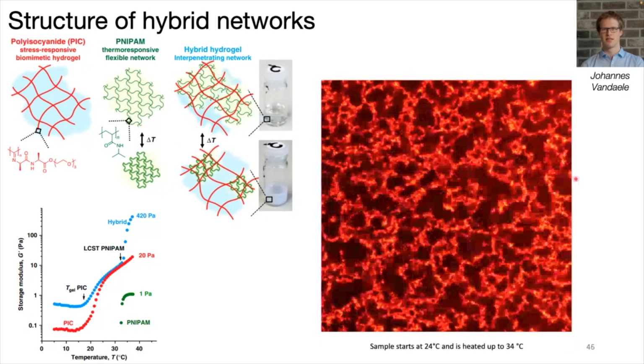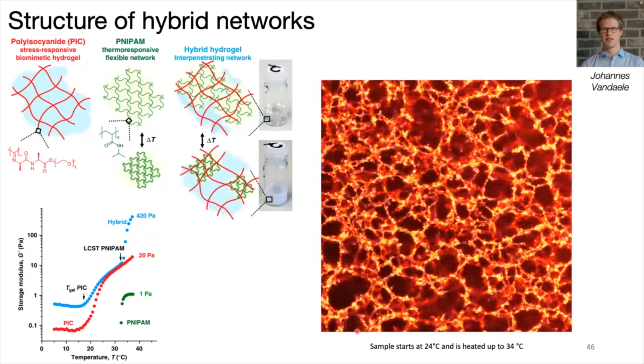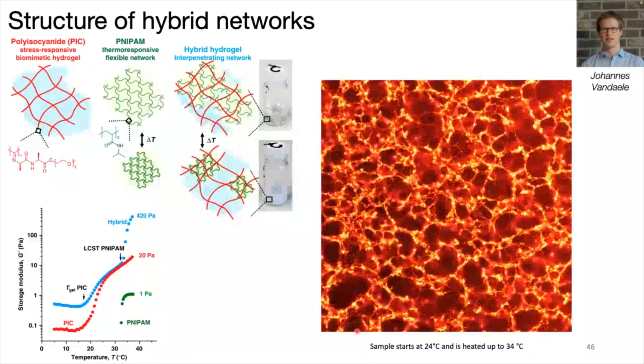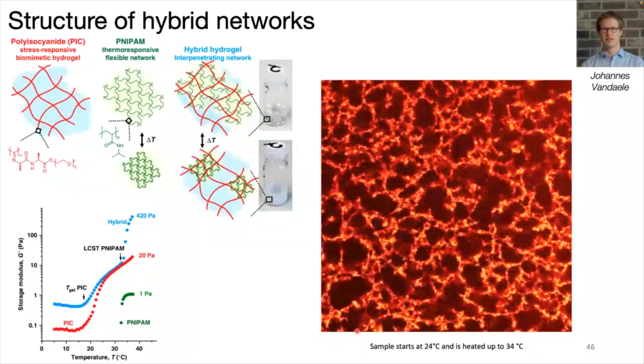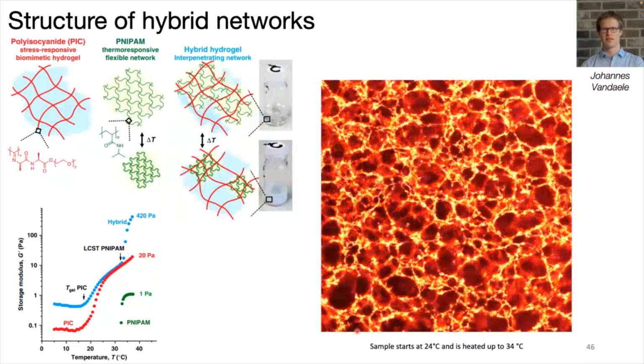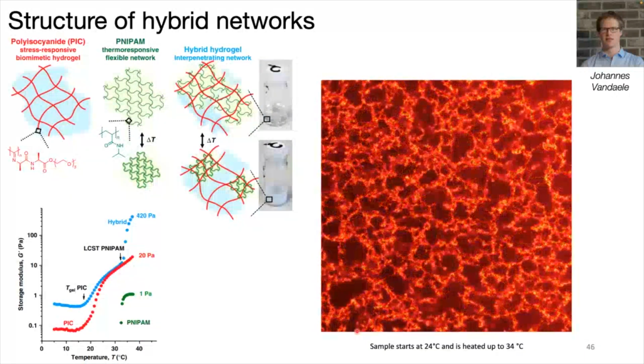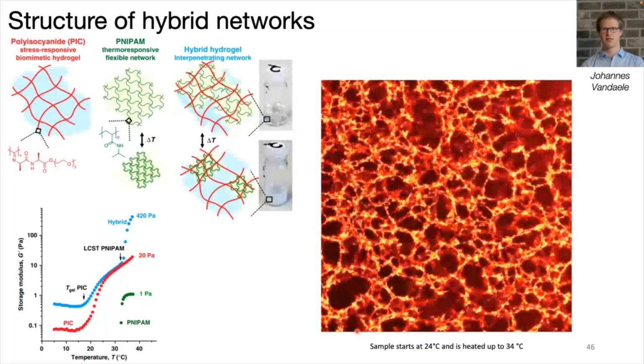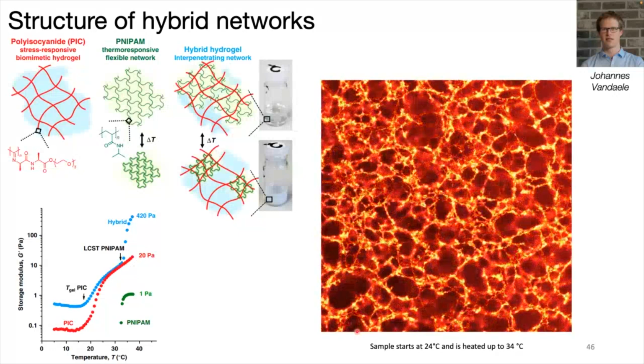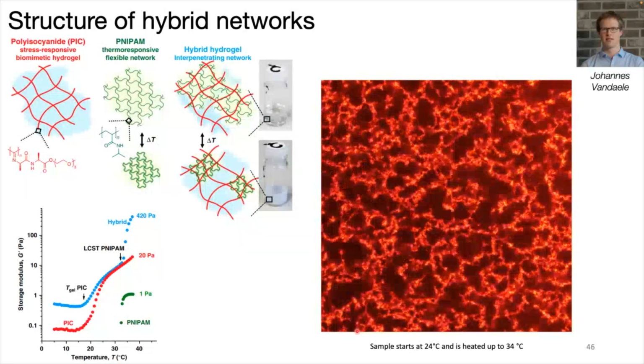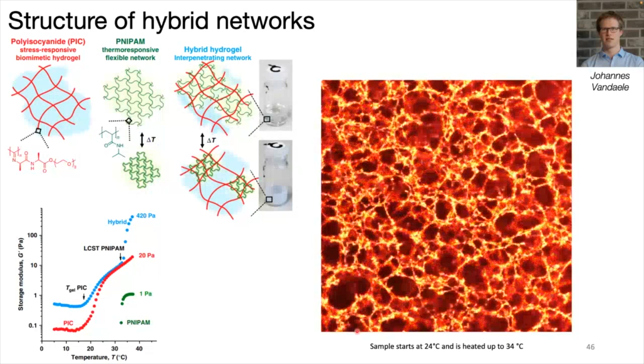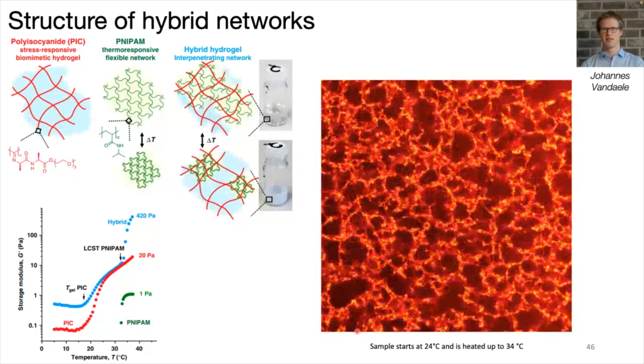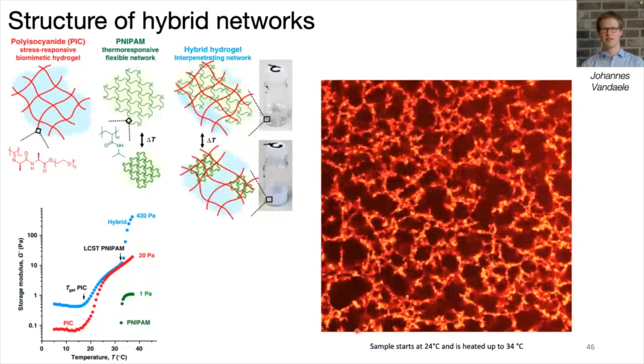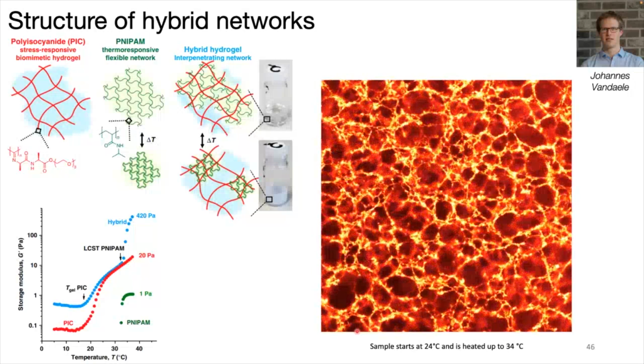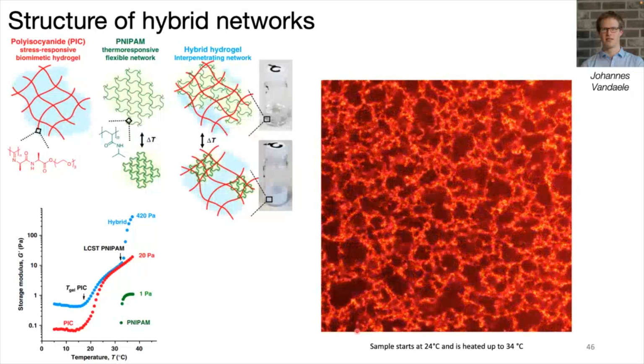And we even have a movie where we warm up the sample. I hope you see the movie. And then you see that it goes from being a broad fiber, and then once you warm it up, the polyNIPAM compresses on the PIC, and you see the PIC fibers become brighter and more compact. So we are now trying to quantify the structural changes using some analysis.